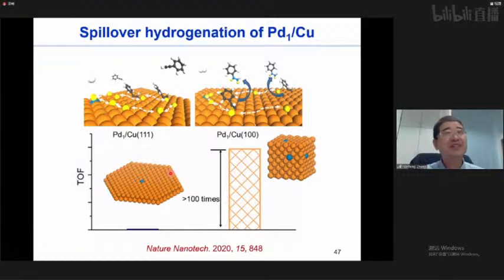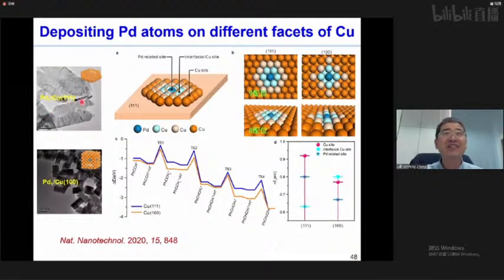So we found that the hydrogenation is highly dependent on the facets of the metal. So basically, in our design, we try to use copper nanotubes with 111 as the exposed surface, as well as nanocubes with the 100 surface as the exposed surface. Okay, and indeed, based on our DFT calculation with Professor Gang Fu, we found that on copper 111, the reaction energy barrier is pretty low. So which means that once hydrogen molecules get activated on palladium into hydrogen atoms, they can spill over to the copper surface. On copper 100, they can do the hydrogenation.